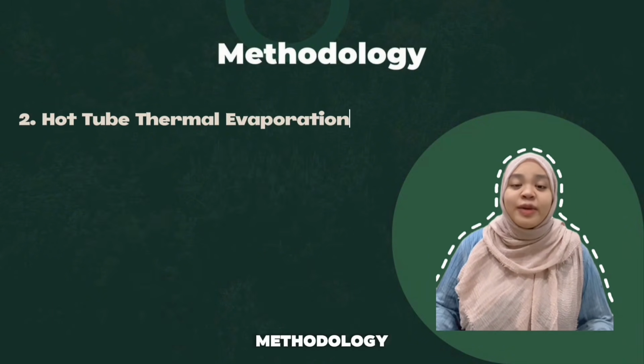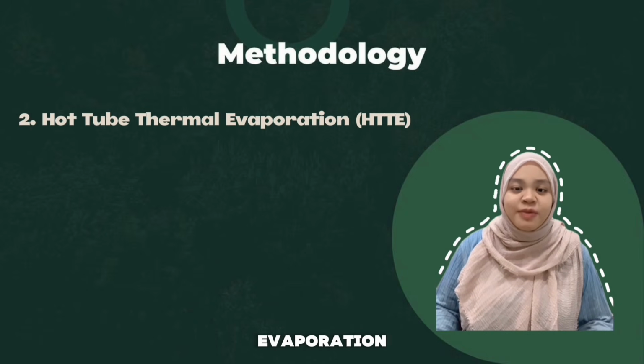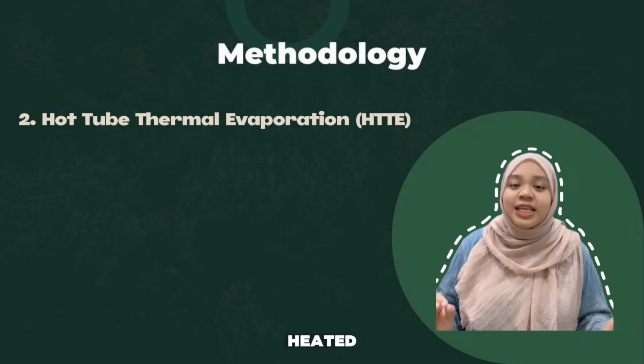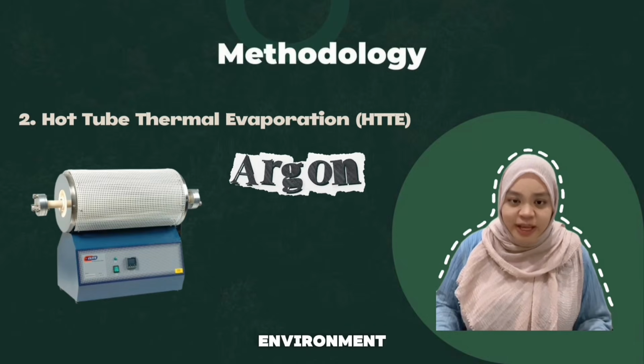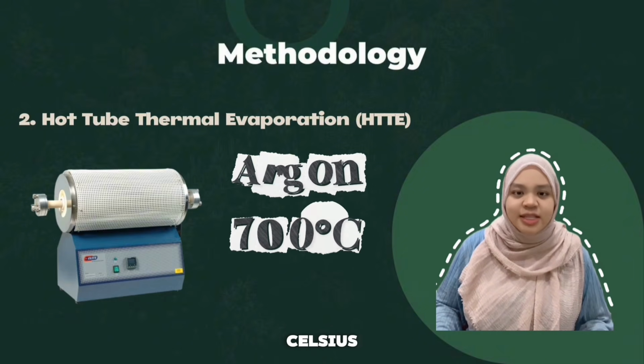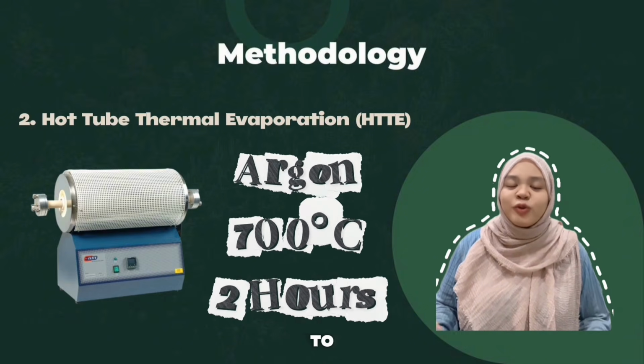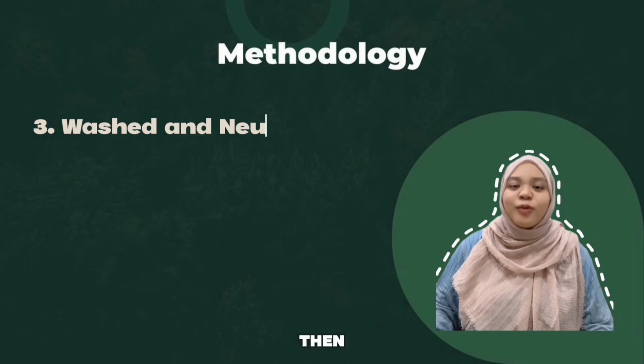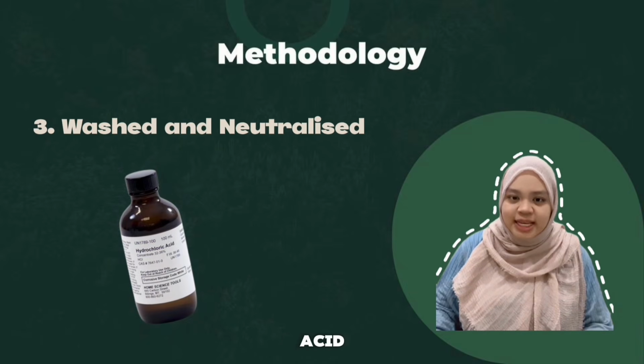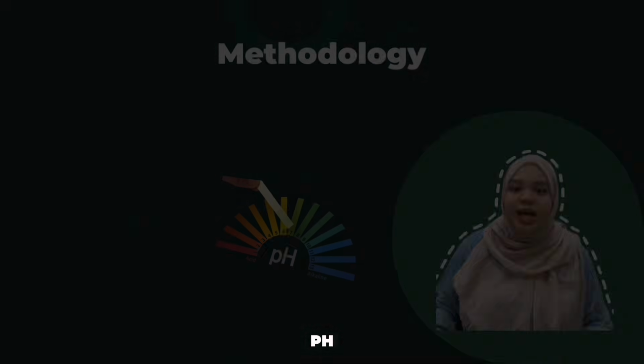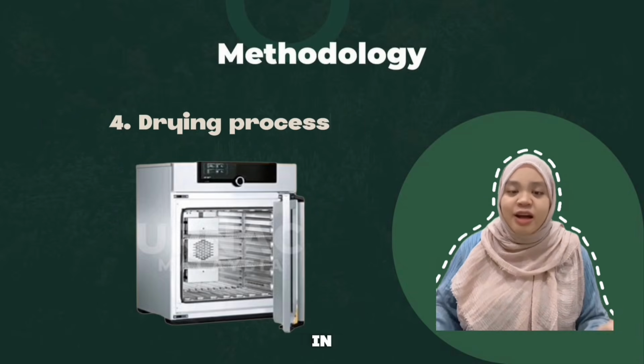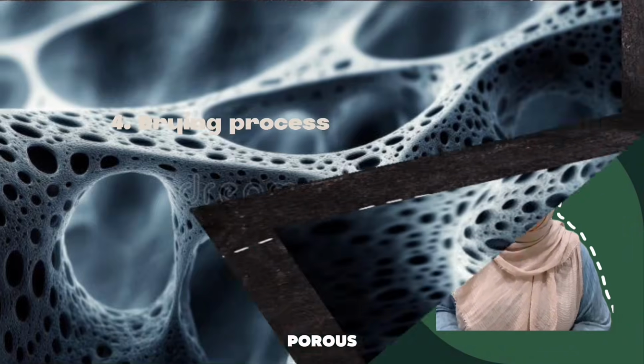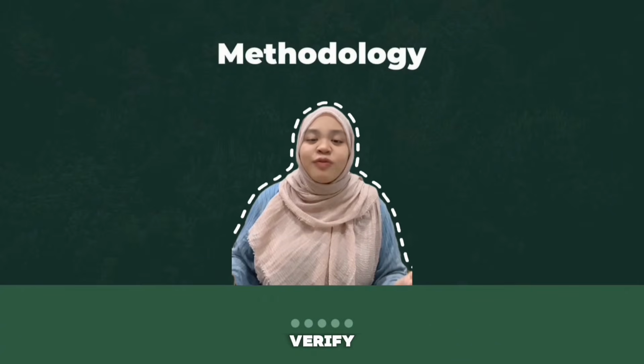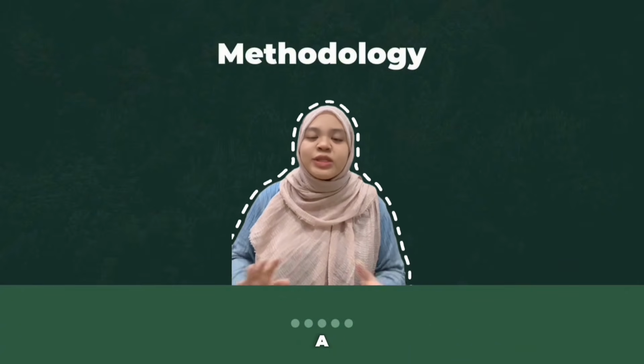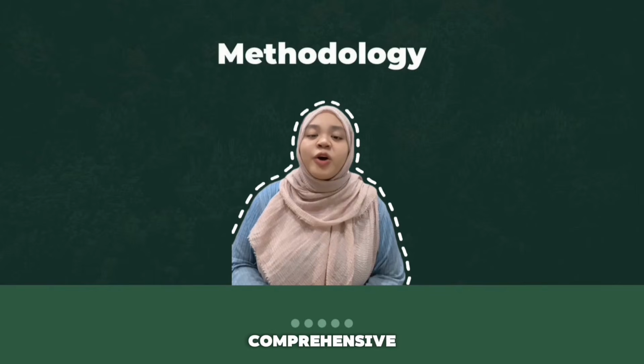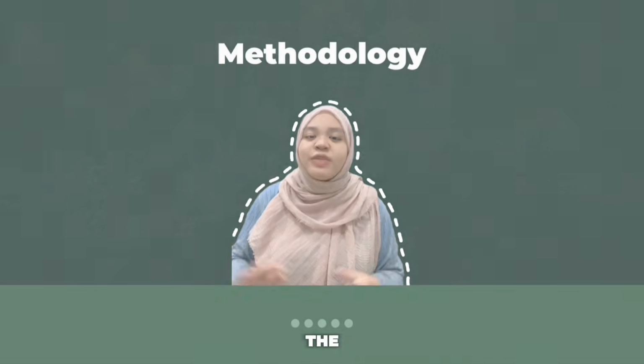The next stage of our methodology is the hot tube thermal evaporation process. The mixture is heated in a tube furnace under argon environment, ramped to 700 degrees Celsius, held for 2 hours and left to cool naturally. The product is then washed with dilute hydrochloric acid and raised to neutral pH. Lastly, the samples are dried in oven overnight to obtain porous activated carbon. Finally, we verify its structure and performance using a few analysis instruments for a comprehensive behavioral study of the sample.